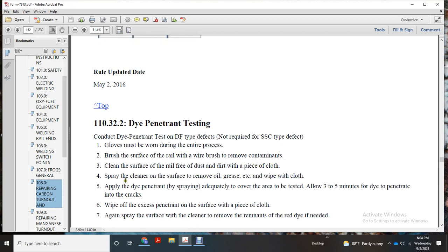Remove the oil and grease. Wipe it off with the cloth. Apply the dye penetrant spray, enough to cover the area to be tested. Allow 3 to 5 minutes for dye penetration into the cracks. Wipe off the excess penetrant from the surface with a piece of cloth.